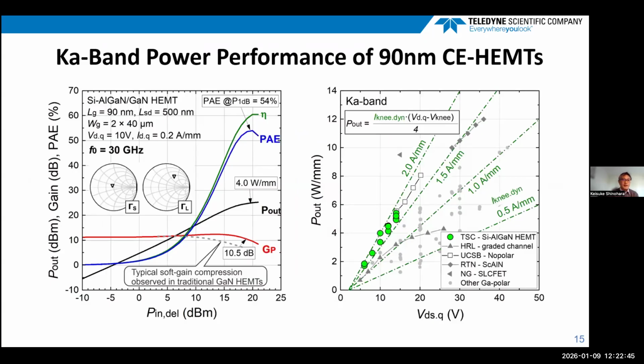Okay, next, I show the load pull characteristic results measured at Ka band at 30 gigahertz. On the left, I show the Pin-Pout characteristics of such a device, and the device shows an output power density of 4 watts per millimeter at a drain quiescent bias of only 10 volts, with an associated PAE of 54%. And as you can see, the gain curve is so linear, and it doesn't show the typical soft gain compression observed in traditional GaN HEMTs. As a result, the peak PAE was obtained at P1dB conditions. So this technology is very suitable for linear power amplifier applications.